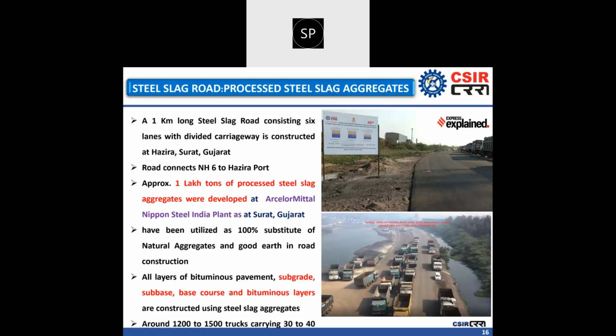So this is one of the major significant achievements. Up to a partial extent, let us say 20-30% replacement of slag has been attempted under CRRI supervision on different projects, and we delivered those projects way back in 2015-16. But in 2021 this project was completed, and in this particular work we utilized 100% processed steel slag aggregate as a substitute of natural aggregate inside the road.